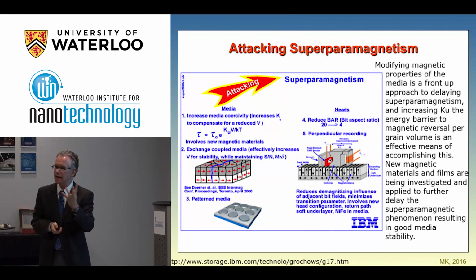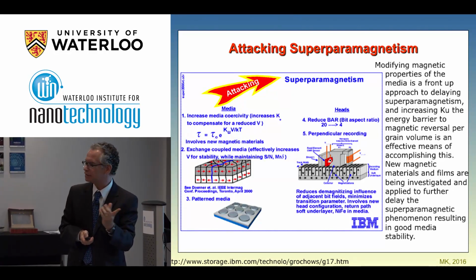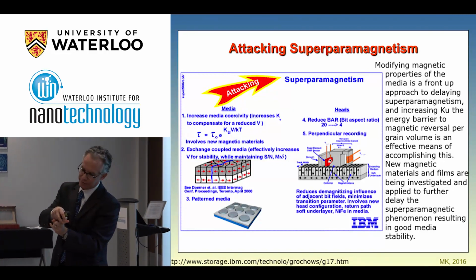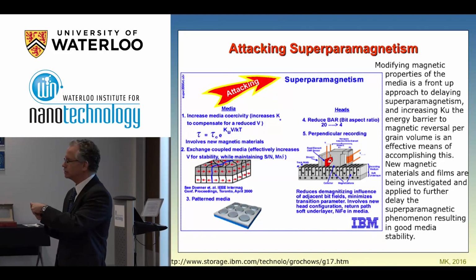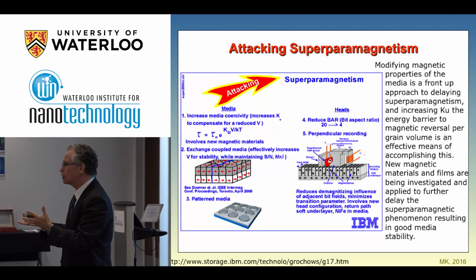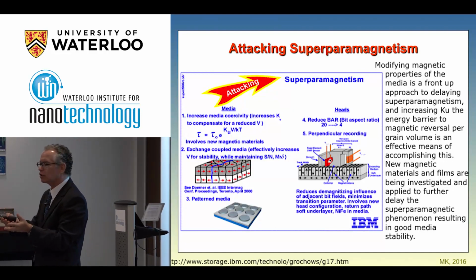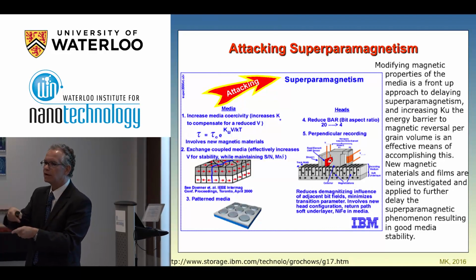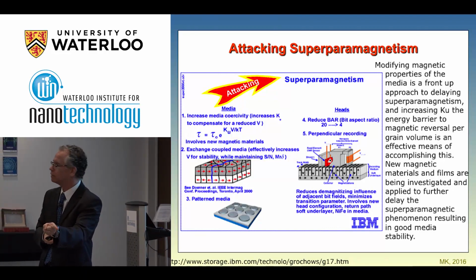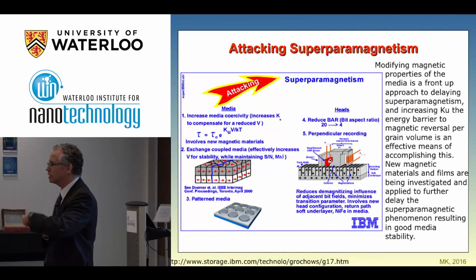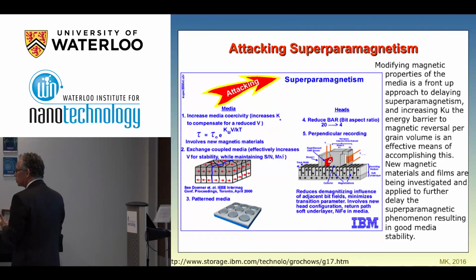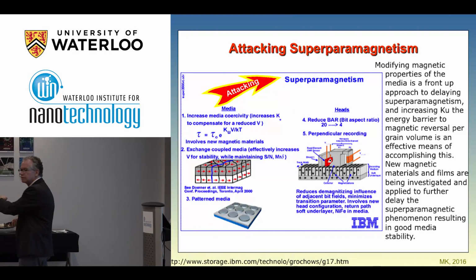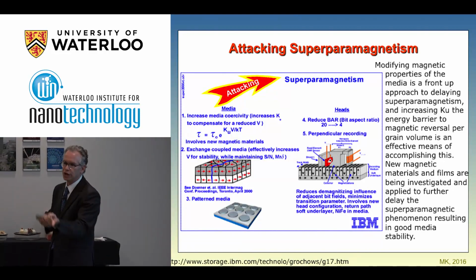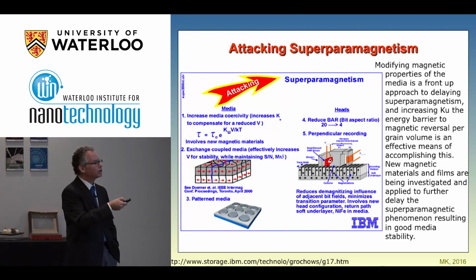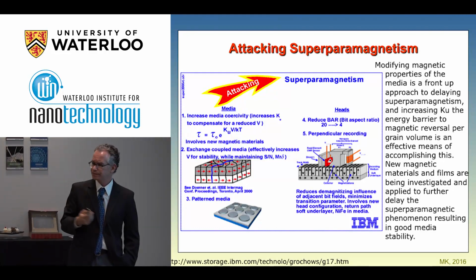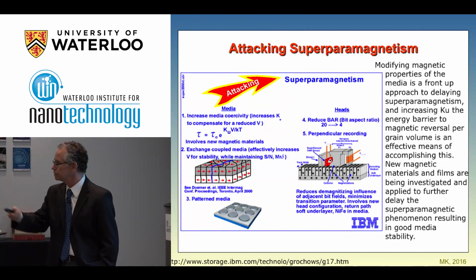The problem is that it became so strong and so hard that not even the field is able to change this magnetic moment. And then you can make a recording of any information, but you cannot write over it. So you keep an information forever, and you cannot change this direction. So the important thing in magnetic recording is not only to record the information, but to keep this information, and whenever it's necessary, to change the information as well. So the problem with hard magnetic materials is to write again in some system.